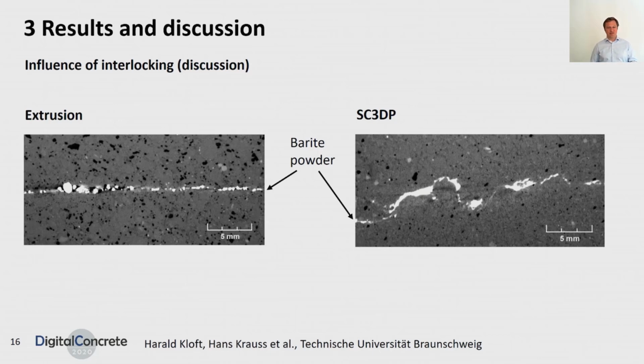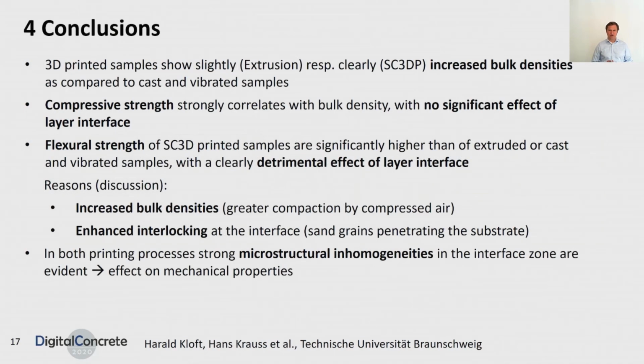In case of extruded specimen, you see a very smooth interface as expected. And on the right hand, you see the image of the interface of a shotcrete 3D printed specimen, which is very rough and hence has an increased contact surface, which may help mitigate some problems we get with cold joint formation by, for example, fast structure build-up, as shown some slides before. And this may, to a high degree, explain the very good mechanical performance, especially in terms of flexural strength of shotcrete 3D printed specimens. So, now I already come to the conclusions.